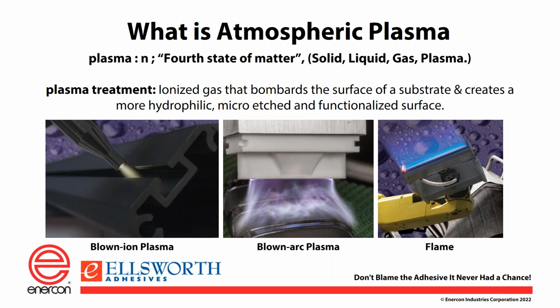We use that to get down into crevices like that. We use it for bonding lines. You use it to treat a lot of different things. It can work on pretty much any material. The blown arc in the middle has to be used on non-conductive materials. Now that's about a 3.5-inch wide head, so it is treating a larger area, but you're generally going a little bit slower, in the order of maybe 10 to 15 feet per minute, whereas the blown ion can go much faster, maybe 100 feet a minute.